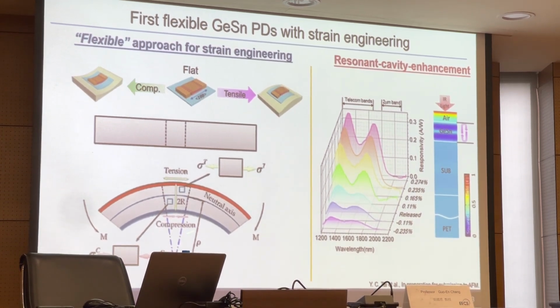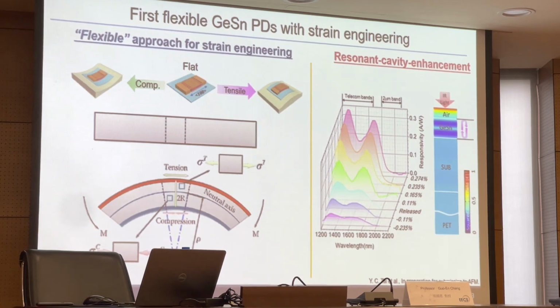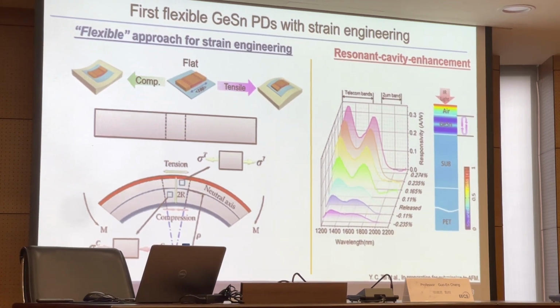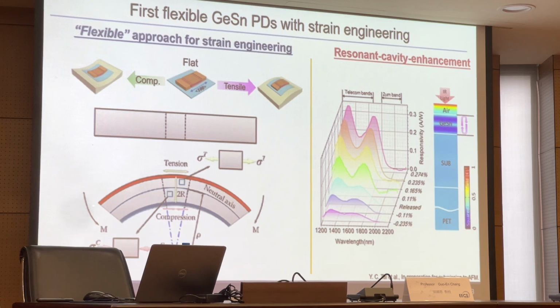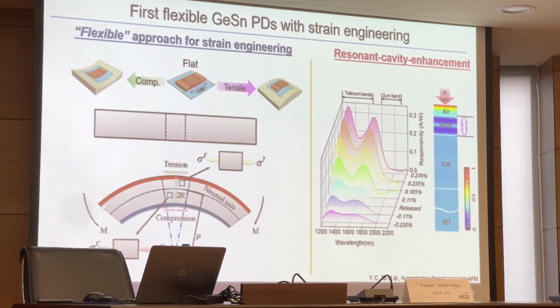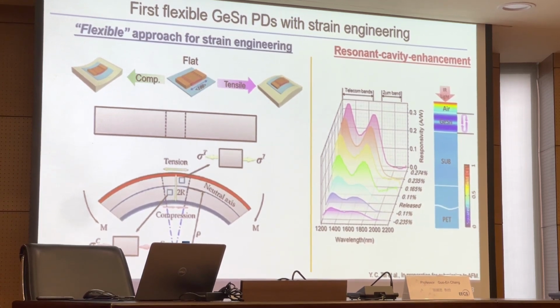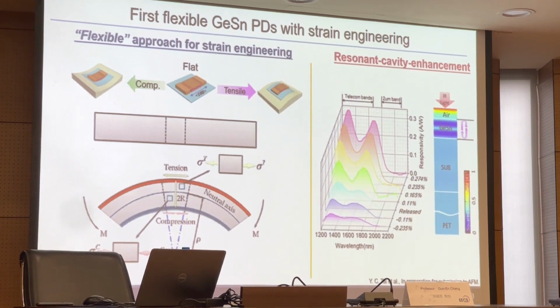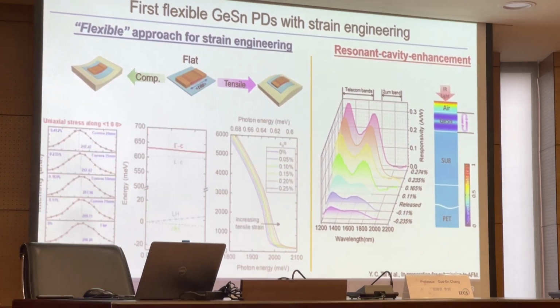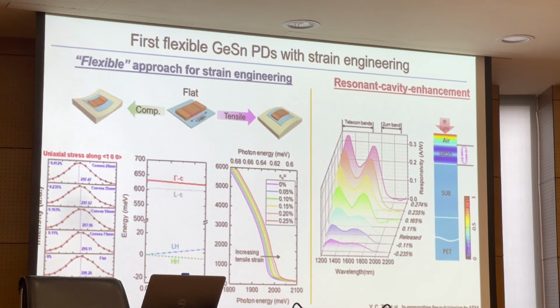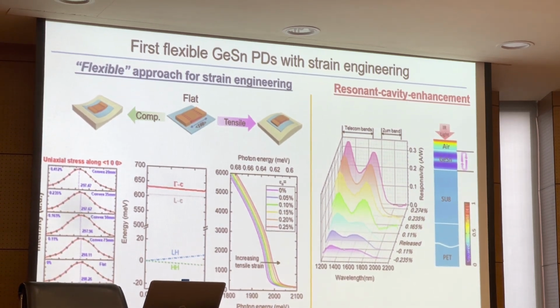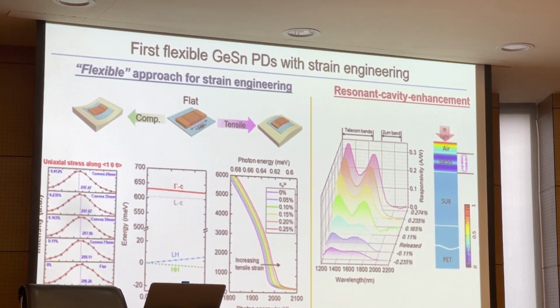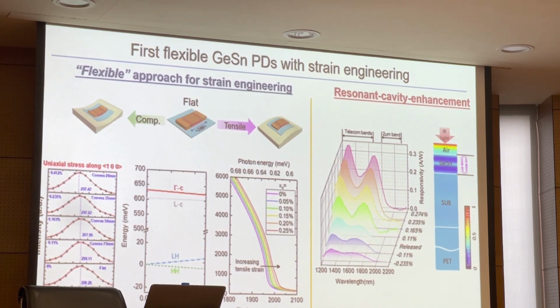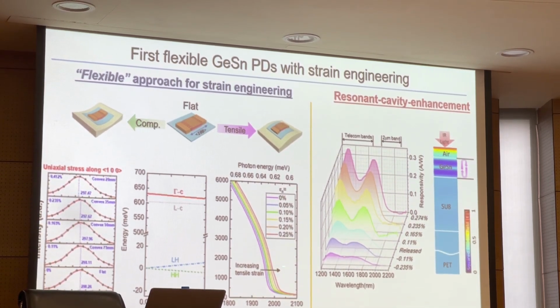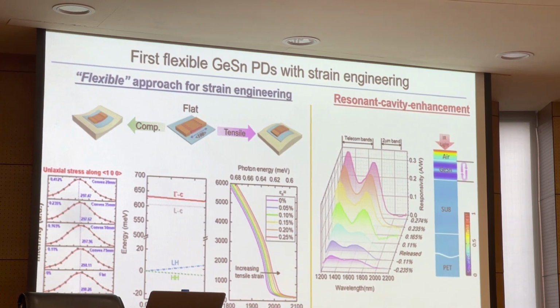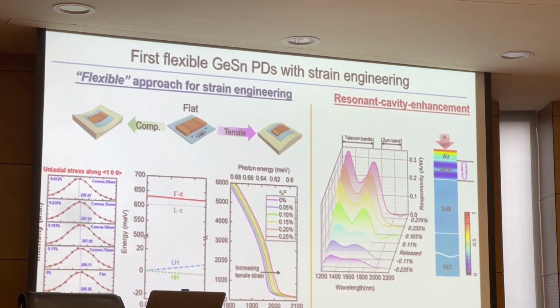Because it is flexible, you can bend it. When you bend it downward on the top, you give tensile strain to the germanium thin film, and this tensile strain further reduces the bandgap energy, pushing the absorption range to longer wavelengths. At the same time, we can enhance the responsivity.